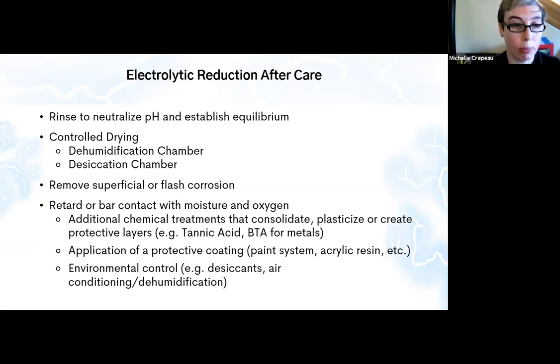We can treat it with additional types of chemicals. We usually use tannic acid for wrought iron and cast iron, for example. It's an acid that reacts with corrosion product and forms a precipitate that basically forms a physical barrier between the artifact and the environment. We use BTA for a similar idea for copper alloys, for example. We also often apply a protective coating on top of that treated layer, such as B72 or an acrylic resin layer or paint layer, et cetera.